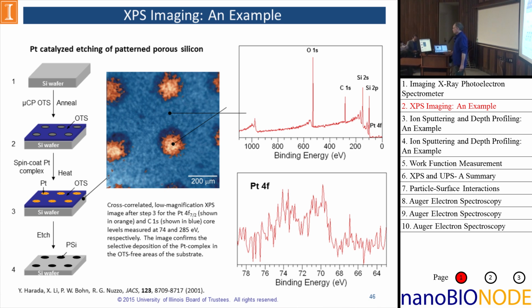Then we could jump out of the imaging mode into the spectroscopy mode, collect some data within a dot. We could see fairly nice platinum signal within the dot, and then move off the dot and actually see quite a diminished signal. We are still picking up a little bit of platinum, so that could either be at the tail of the spot that we're analyzing, or we are getting small amounts of platinum depositing up around the surface.